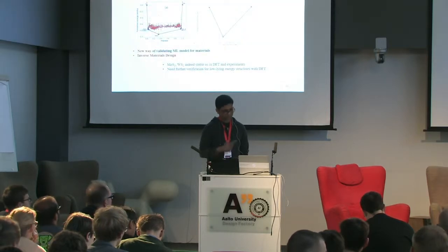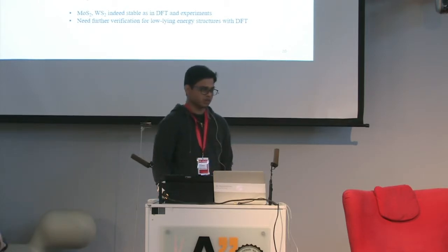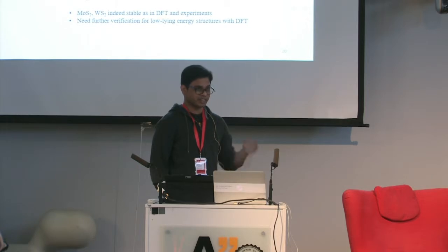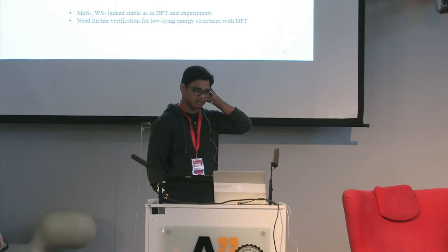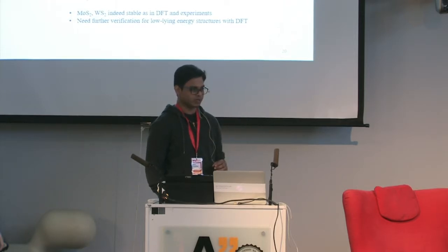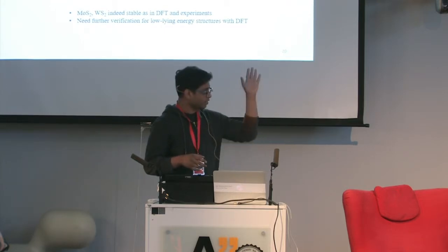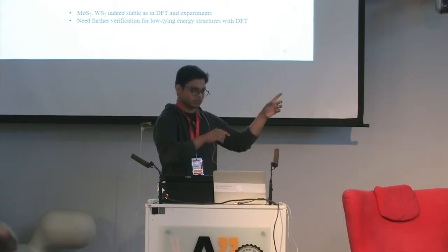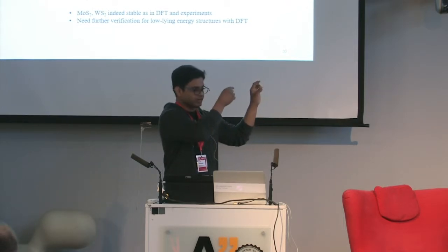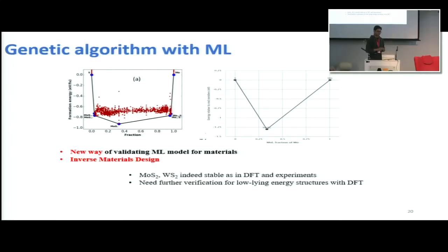Yeah, here the genetic algorithm will be helpful. So basically, suppose you want to design a nickel aluminum system, or nickel aluminum cobalt. Take 5 components: nickel, aluminum, chromium, iron, whatever 5 elements. You want to find a golden additive manufacturing alloy there. What you would do is you let them combine using a genetic algorithm and machine learning model and find your convex hull. And on the low energy state, it will predict the structure also. So there you will do only DFT calculation on low lying structures. And based on that, that will give you what is your favorite alloys in that composition.